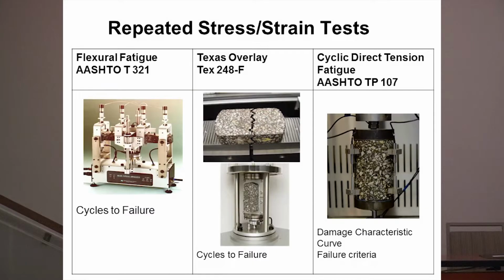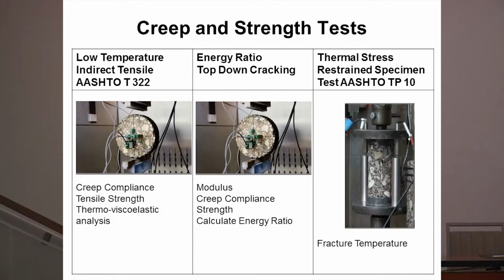More recently, primarily research out of North Carolina State, and a lot of it is being funded by the Federal Highway Administration, is looking at the cyclic direct tension fatigue test, AASHTO TP 107. What is done here is you get a characteristic curve. All of the materials or the asphalt mixtures tend to damage in a certain way. You also get a failure criteria from it, and it's another type of repeated loading test. There's a series of creep and strength tests.